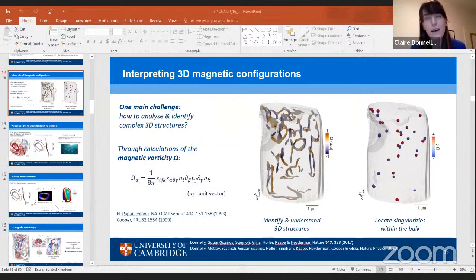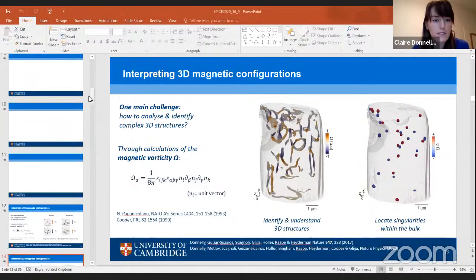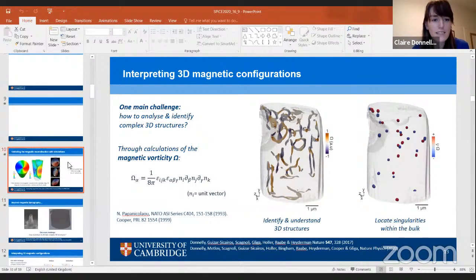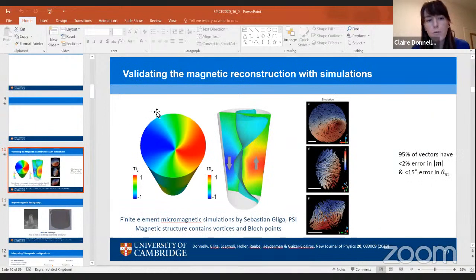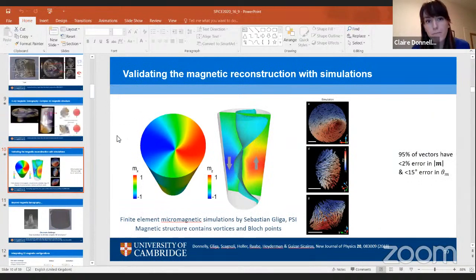That's a really good point. So we almost have another added challenge when it comes to 3D. I showed the example when we're looking at some micromagnetic simulations. One of our collaborators had performed some calculations to determine the exchange length, and that's what we use. So we model it essentially as a kind of soft ferromagnet. We don't take the full ferromagnetic structure behavior into account.